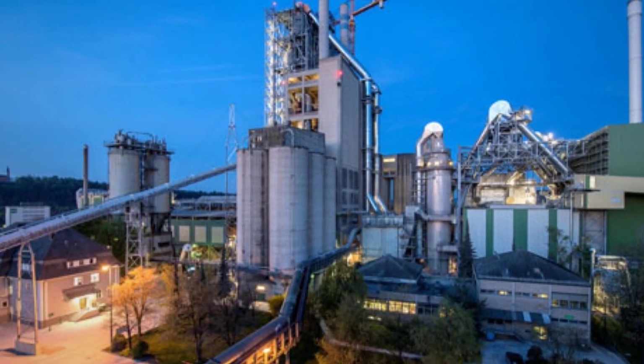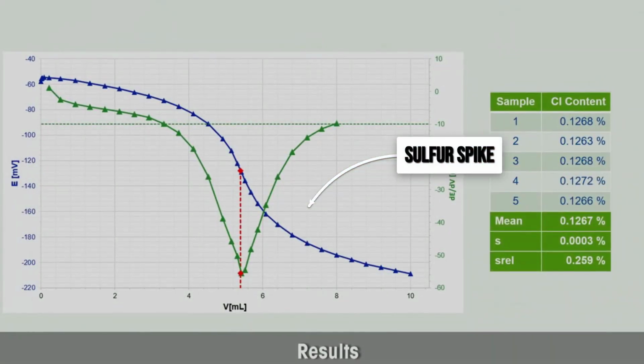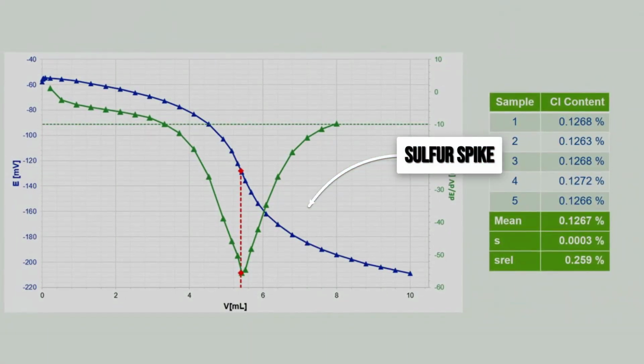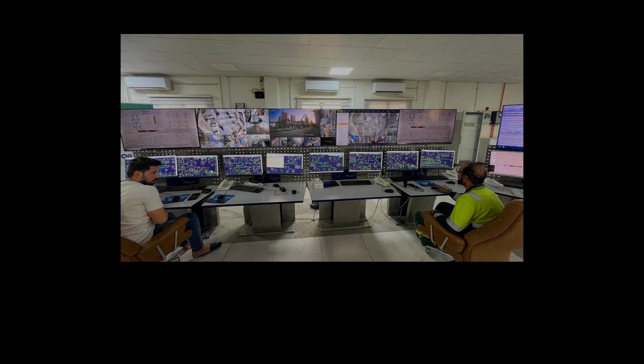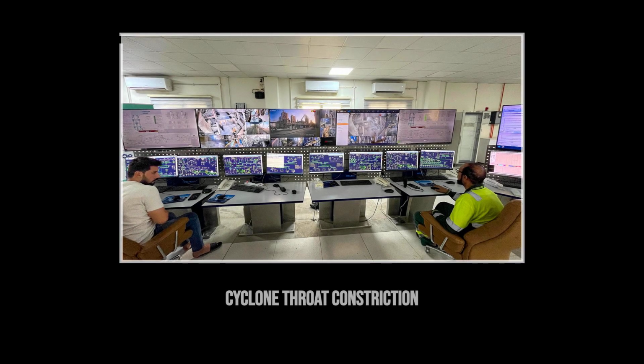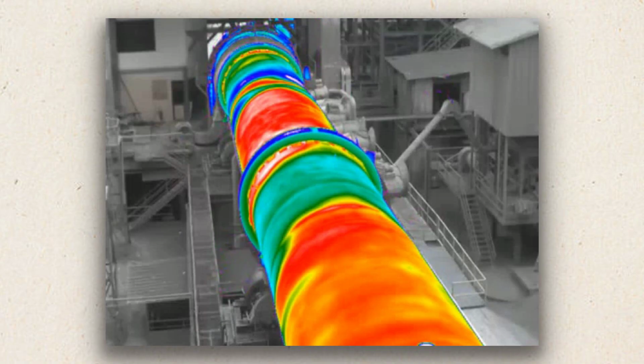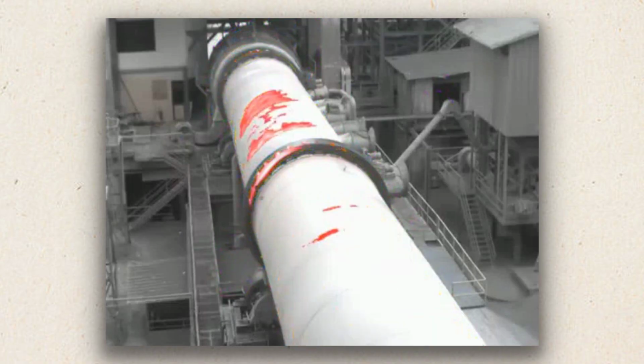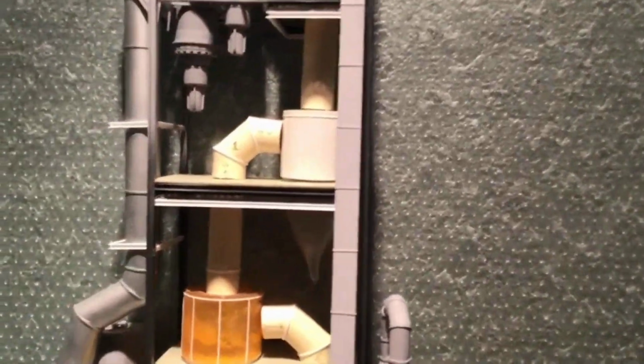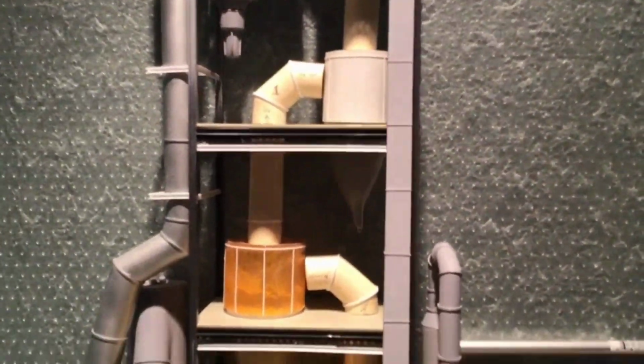But even the best design faces challenges. A sudden spike in sulfur or chlorine from the raw mix can trigger sticky deposits, narrowing the cyclone throats and raising pressure drop. The infrared scans pick up these hotspots first. A bright flare at stage 3 signals a potential blockage.